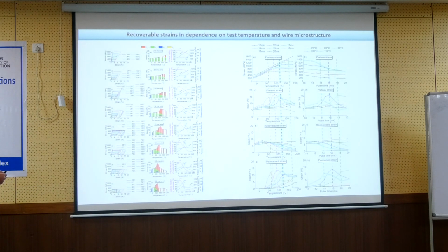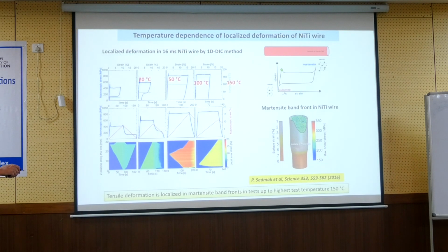With this phenomenon of plasticity, the more you anneal the wire, the more you will have it. The reason for having this maximum of plateau strain is that the martensite, which is created by loading, will at the same time deform plastically and create these deformation bands in the microstructure. So while it transforms, inside this propagating band, if it is at high temperatures, around 50 degrees C, the martensite deforms plastically. But the problem is why it decreases with further increasing temperature.